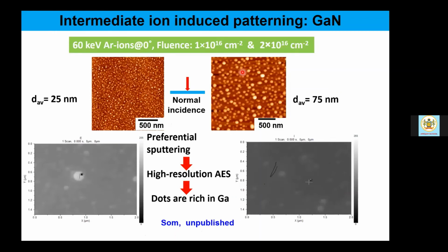Same situation almost for gallium nitride. This nitrogen gets much more preferentially sputtered, giving rise to these dot formation which are heavily rich in gallium. And that was actually observed by high resolution Auger electron spectroscopic measurements. Dot size increases with ion fluence. Okay, very clearly, but 25 nanometer was the average dimension here for dots, which turns out to be nearly 3 times more upon increasing the ion fluence by 2 times.